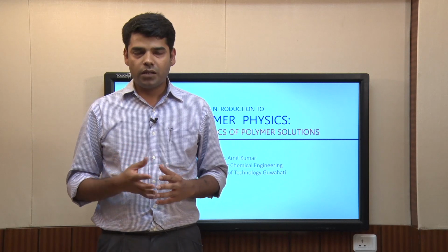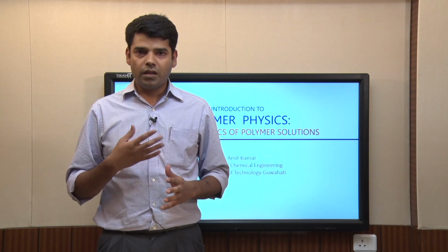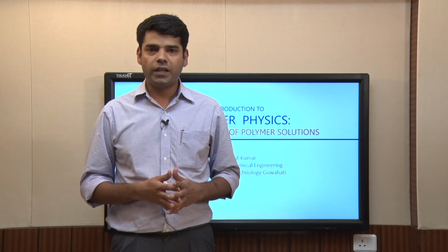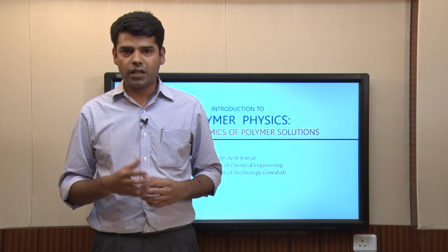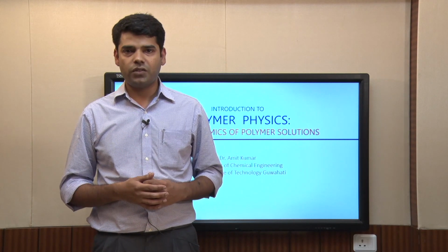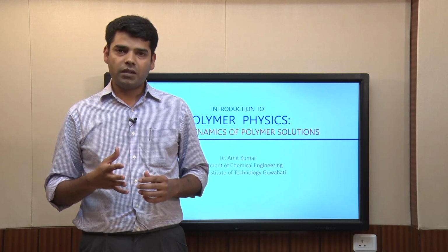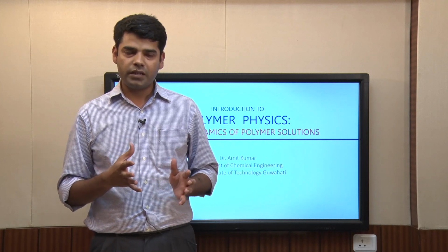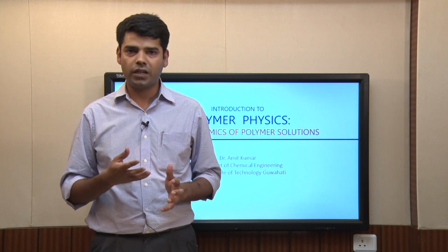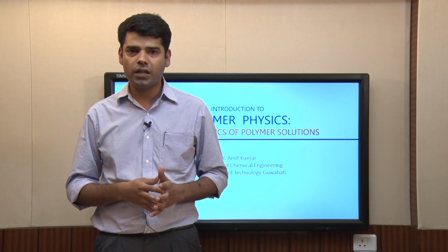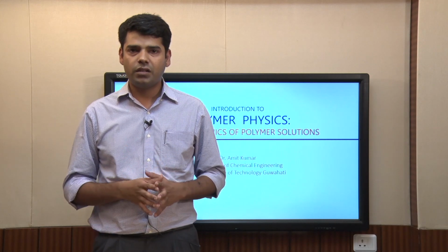We also introduced a parameter called the Flory-Huggins interaction parameter, or the chi parameter, which is a measure of the polymer-solvent interaction, and this parameter also appears in the expression for the Gibbs free energy change of mixing. The chi parameter itself incorporates the effect of the type of lattice that is chosen for the development of the Flory-Huggins theory, as well as the contact Gibbs free energy change.